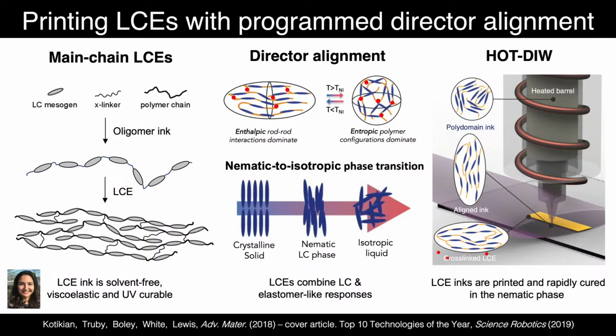So I talked about how we make these liquid crystal elastomers. We combine polymer chains with liquid crystal mesogens, and we have cross-linkers that introduce light cross-linking. This was the work of a very talented PhD student, Arda Kotikian. We designed an ink that was solvent-free, viscoelastic, because that's what we need, and UV curable.